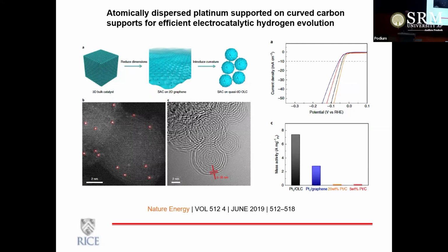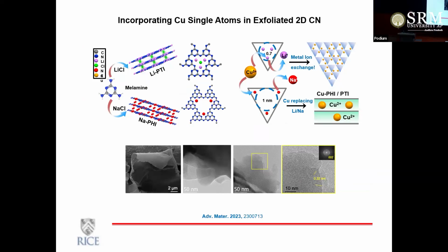If I put single metal atoms in these carbon supports, you get much more efficiency in the catalysis, like the hydrogen evolution reaction. The other challenge, or emerging field, is to controllably place single atoms of any particular kind in the host lattice. This is not just from our group; many groups today are trying to incorporate single copper atoms in carbonaceous lattices, so porous carbons. This approach gives you two-dimensionally polymerized graphitic carbons with specific sizes of holes in them, and by ion exchange and other techniques, you can introduce metal atoms in these holes.